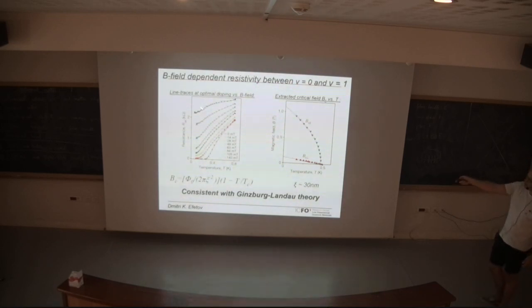Okay, so basically from this data one can extract the critical field. Again, as in perpendicular field, one can really see that the critical field we can extract as a function of temperature follows the Ginzburg-Landau theory. So this linear temperature dependence disappears at Tc, and basically also from this relation we can extract